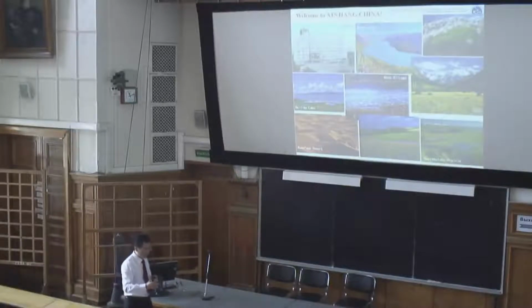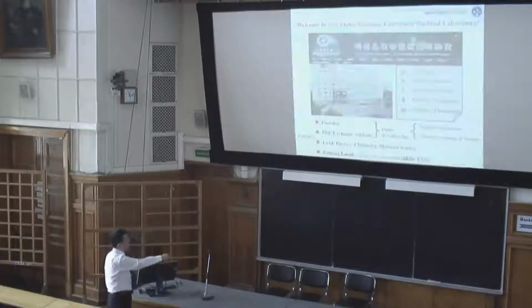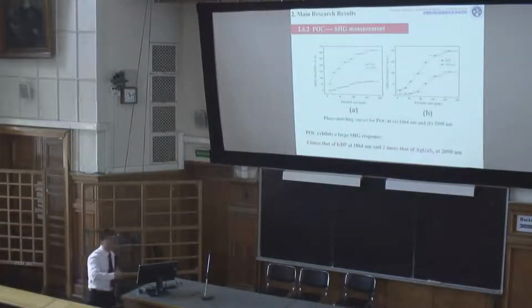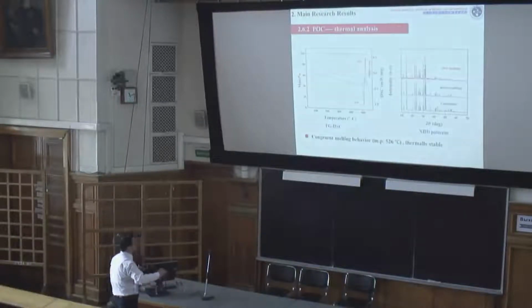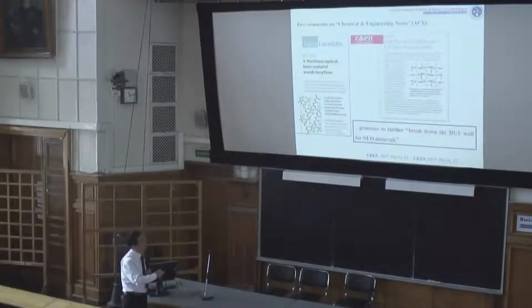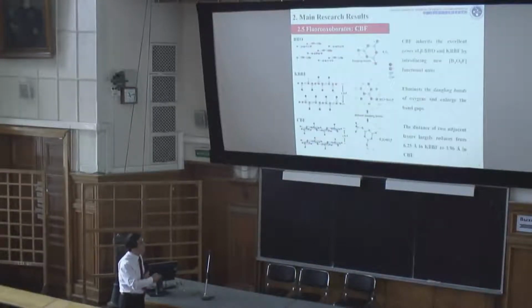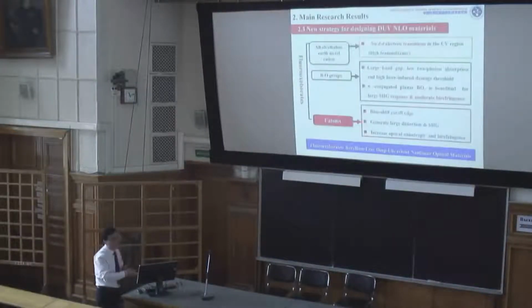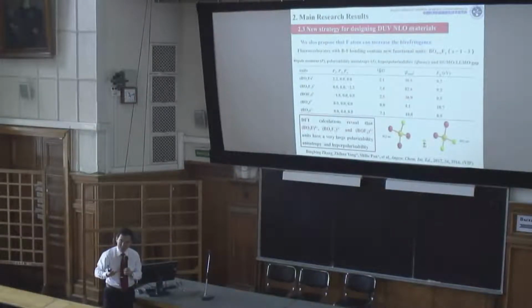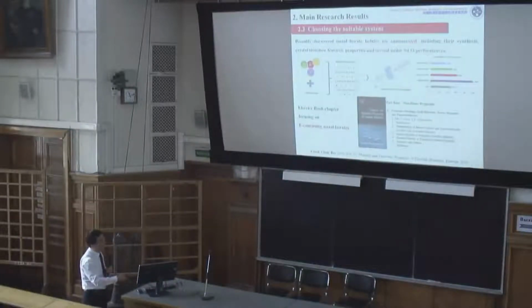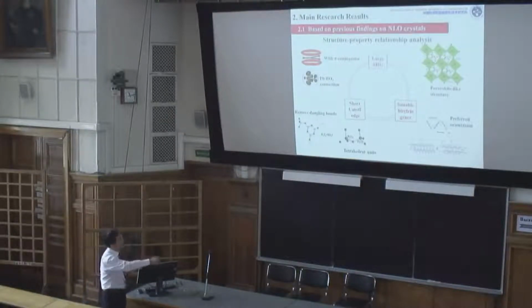Okay, it's a good question. In fact, the first step is we search for compounds with interesting structures, and then we evaluate their linear and nonlinear optical properties. After that, we focus on maybe one or several compounds. We want to grow large crystals. For example, potassium borate chloride, the KBOC crystal. This compound has a perovskite-related structure. We grow a large crystal of KBOC. The KBOC compound was found by Professor Belokoneva. This compound has very interesting properties.